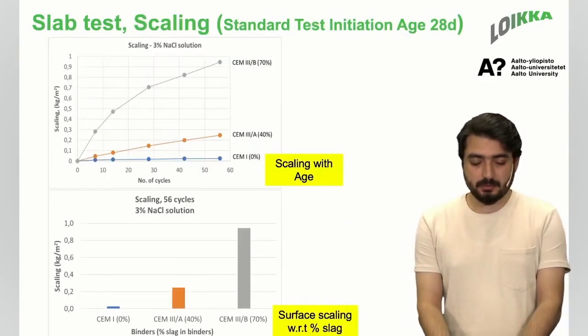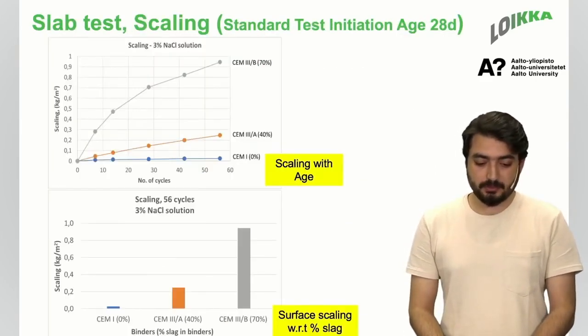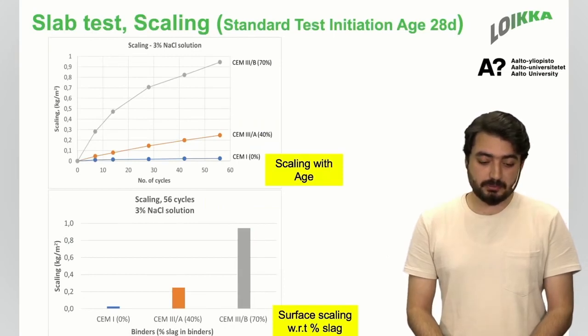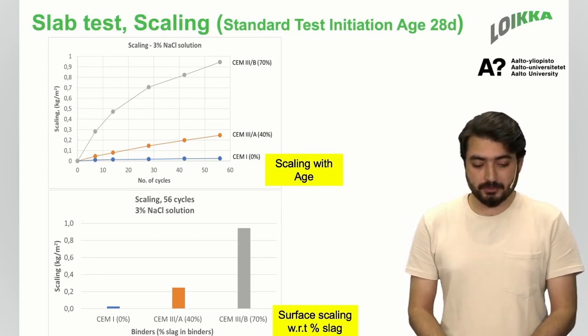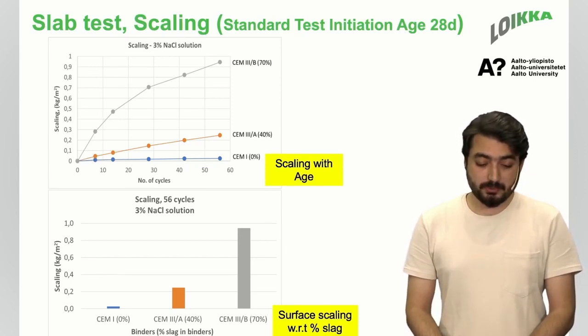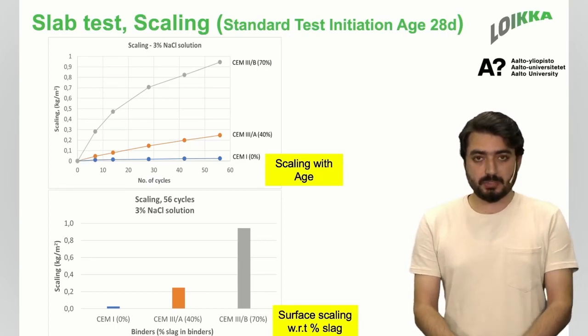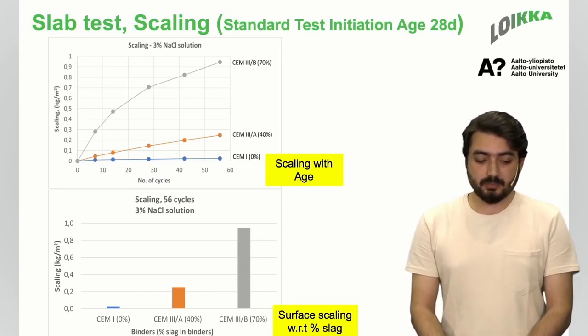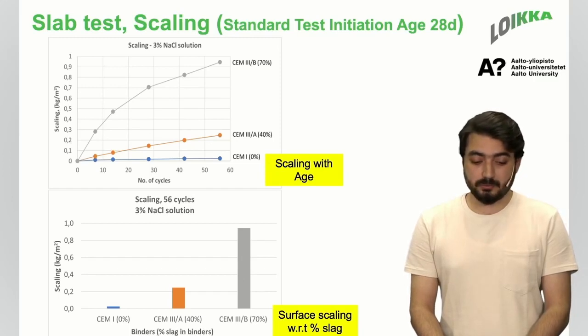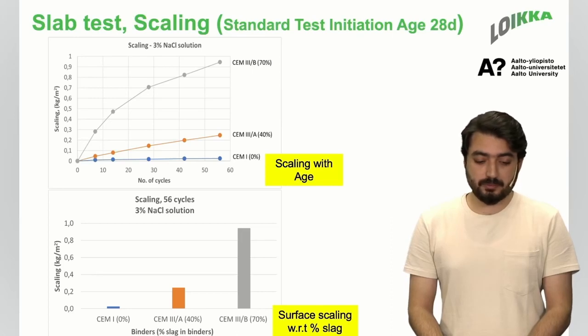So currently we finalized the first normal testing that was initiated after 28 days, and basically these are the same results that I showed during phase 1, and it confirms the behavior for all the 3 cements. So we can see that with no slag, the scaling in kilograms per meter square is quite low, and as we increase the slag content, the scaling of the surface that is exposed to freezing and thawing increases as well.